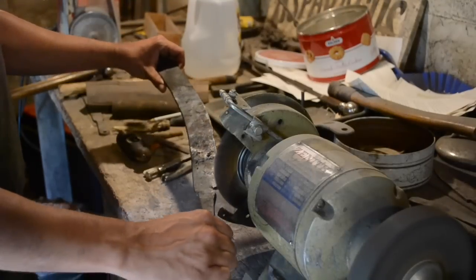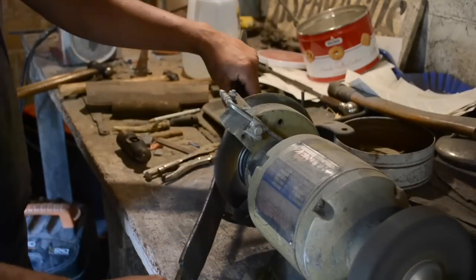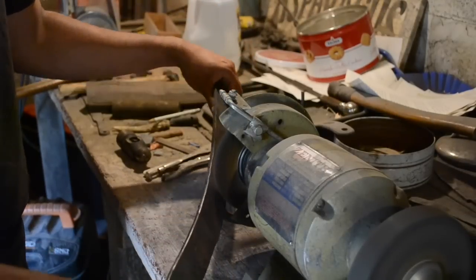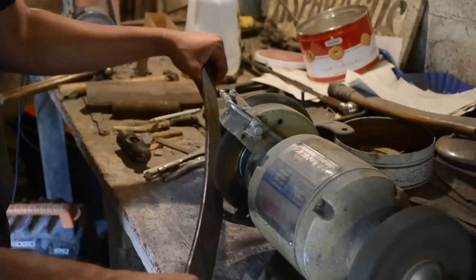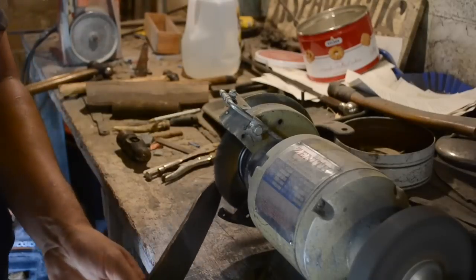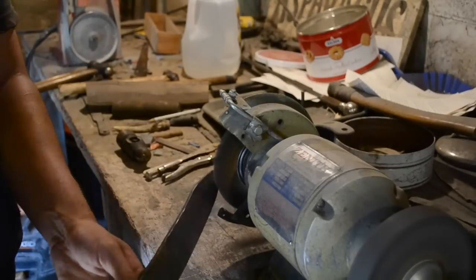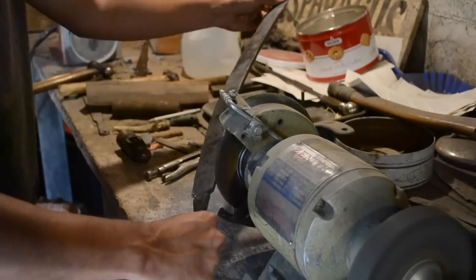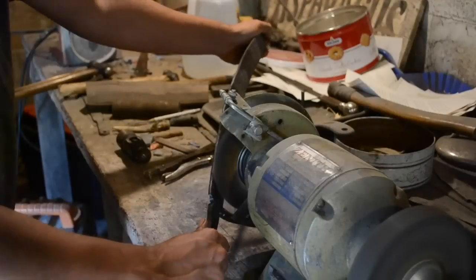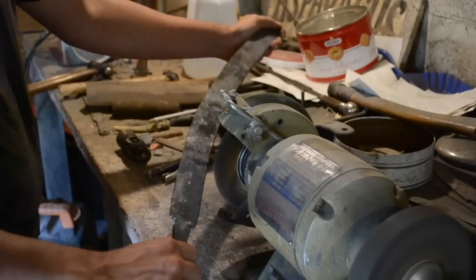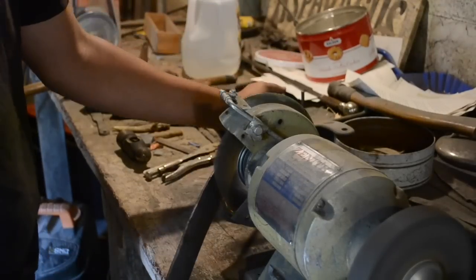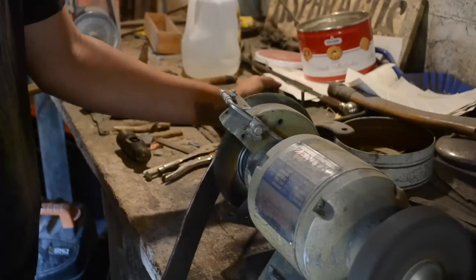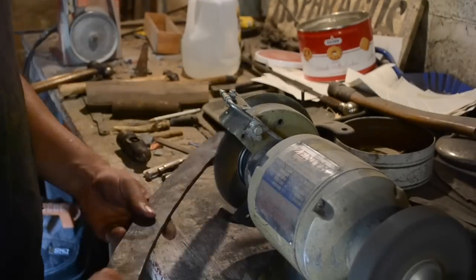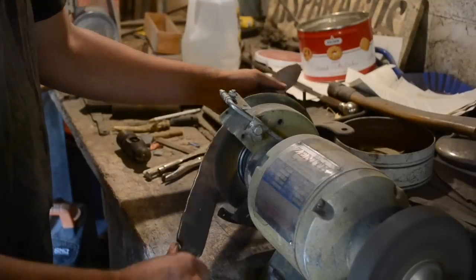Before grinding, I'm going to go over the blade with a wire brush. This will remove the worst of the mill scale. Mill scale can often be quite a bit harder than the steel underneath, so if you can remove it, it will save you some lifespan on your sanding belts. Some people will instead soak the blade in a heavy acid to remove the mill scale completely. I don't like to work with acids because they're dangerous. I would rather put in a little bit extra work on the grinder and not melt my shoes.